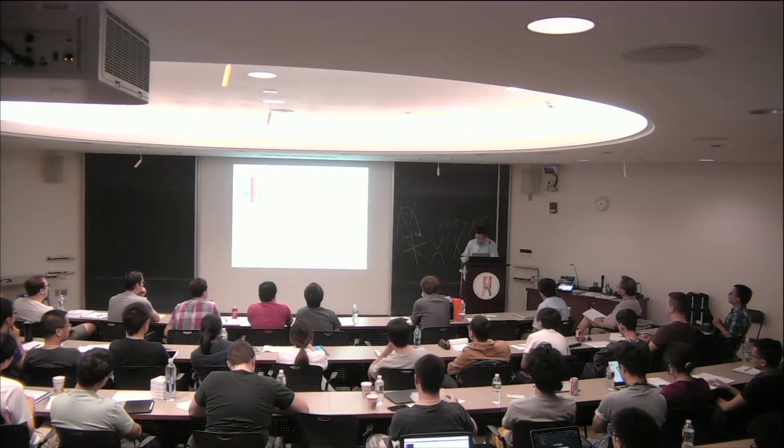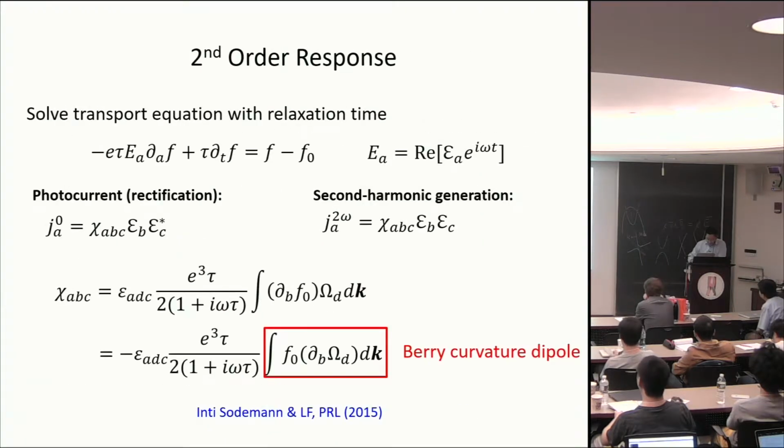Yes. Experimentally, was the frequency dependence measured? Right, that was also measured. In the transport regime, the frequency went all the way to maybe a few kilohertz, and it roughly stays constant. And that is all consistent with the fact that omega is still much smaller than 1/tau. What if the frequency goes to, say, megahertz or even gigahertz? Then actually, according to this formula, it should decrease. So the frequency dependence is basically just like the Drude peak. This behavior is the same as in Drude theory.